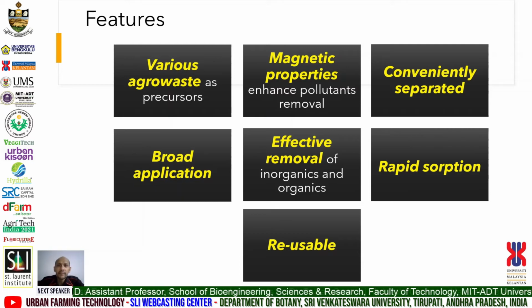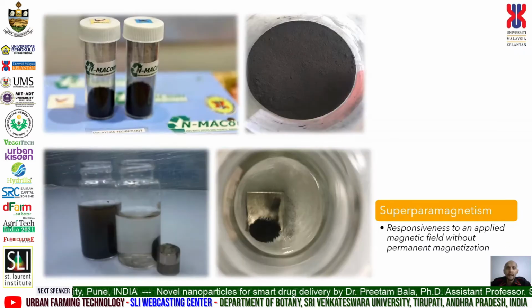Magnetic biocarbon can then be conveniently separated by use of external magnetic field, hence ease of after-use separation or recovery of spent material. And the material is reusable up to 3 to 5 cycles with more than 80% effectiveness retained with material recovery option. Up close with the hybrid composite material, responsiveness to external magnetic field was observed, indicating superparamagnetism characteristic.